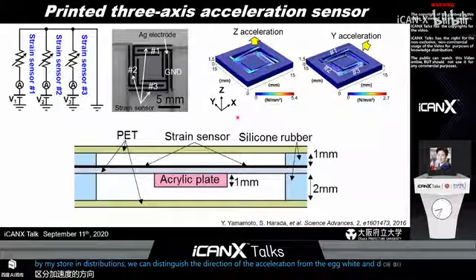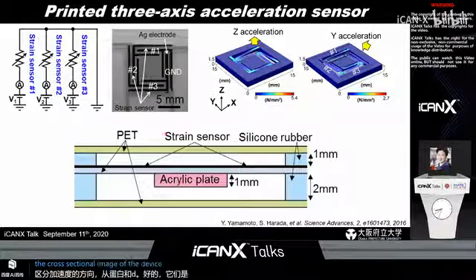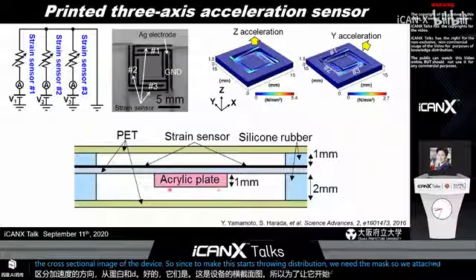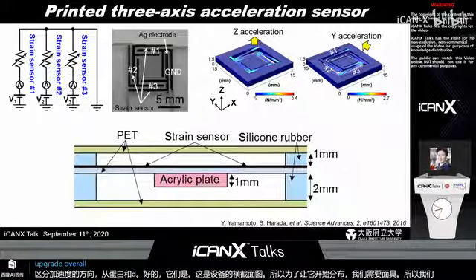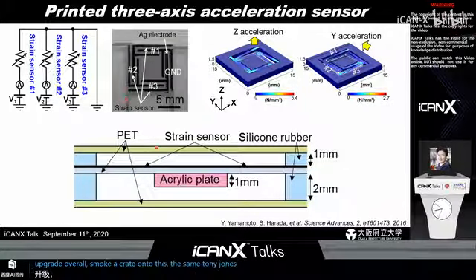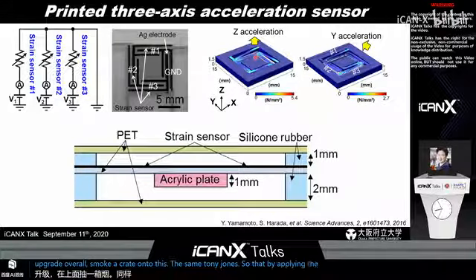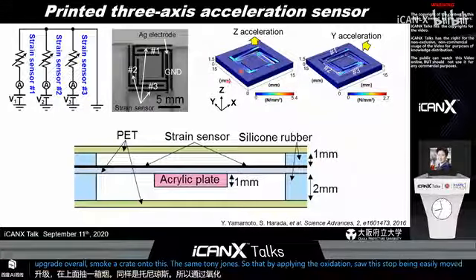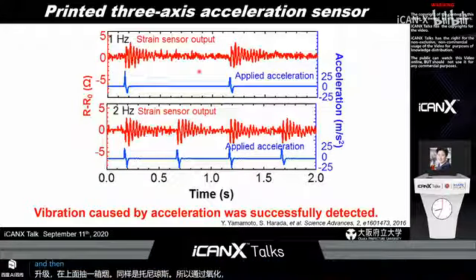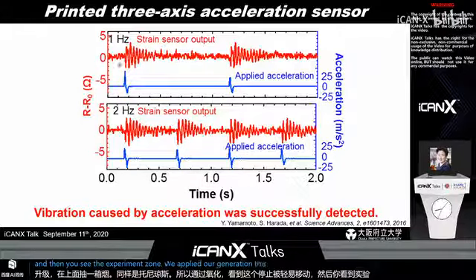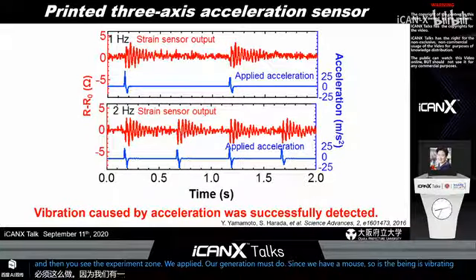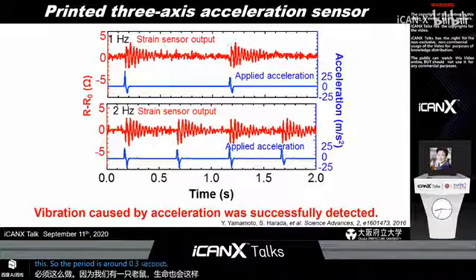And then this is the cross-sectional image of the device. To make this strain distribution, we need a mass. So we attach a small acrylic plate onto this center region, so that by applying the acceleration, this beam can easily move. And then this is the experiment result. Once we apply the acceleration, since we have the mass, this beam is vibrating like this. The period is around 0.3 seconds. And then we can measure the resistance change.